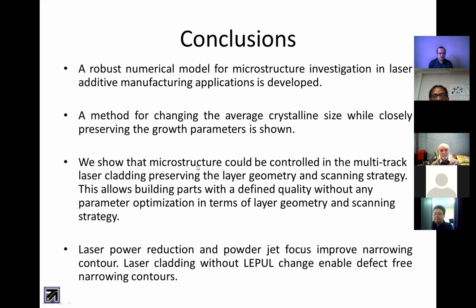We developed a robust numerical model for microstructure investigation in laser additive manufacturing applications. We showed a method for changing average crystalline size while closely preserving the growth parameters. We also show that the microstructure could be controlled in multi-track laser cladding. And this allows us to build parts with a defined quality without any optimization of layer geometry and scanning strategy.